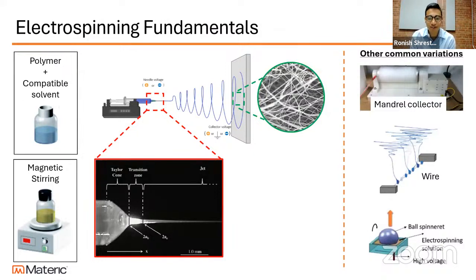This is an events webinar, so you all must be very familiar with electrospinning, but just to briefly go over the fundamentals of electrospinning. Here we have a polymer or a plastic that is mixed in a compatible solvent. It is homogeneously mixed either by magnetic stirring or any other method. Then that mixed polymer solution is extruded through a needle to the tip of the needle, and the tip of the needle is charged with an electrical field.